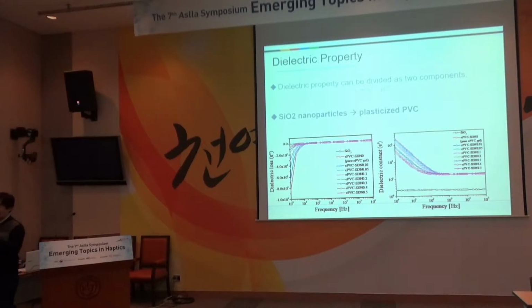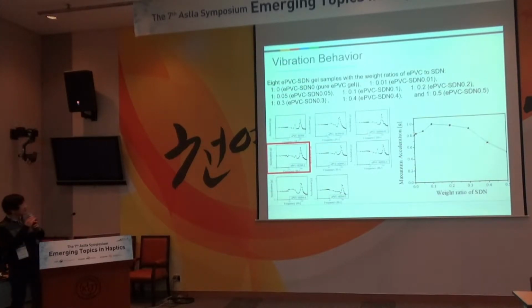So we inserted silicon dioxide nanoparticles into the plasticized PVC gel and tested it. A weight ratio of 0.1 has the best performance.